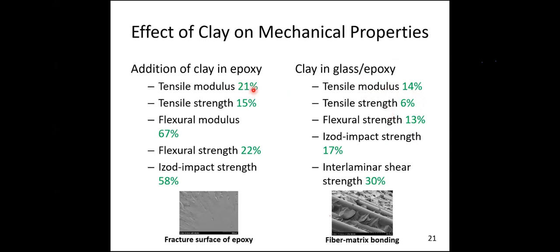If you see the numbers, in epoxy the improvement is high, whereas in glass epoxy the improvement is a bit lower. The reason is, as you all know, in tensile loading the fiber is the dominating mode of failure. The fiber will take the major amount of load, whereas the matrix is secondary. That is why, in the tensile test of glass epoxy clay nanocomposite, the fiber is the main element to take the load.